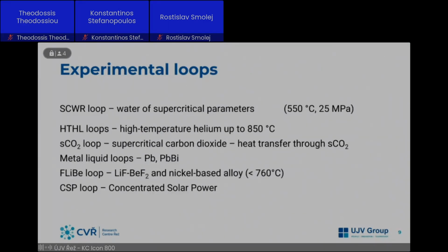Nowadays, what we have is a supercritical water loop, which goes up to supercritical parameters. There is still the possibility to get even to ultracritical parameters out of pile. We have helium loops. There are a few of them, and they are now ready to go up to 850 degrees C, and we are planning to reach 1000 next year. We have a supercritical CO2 loop. This is mainly for testing different heat exchangers and using CO2 as a coolant.